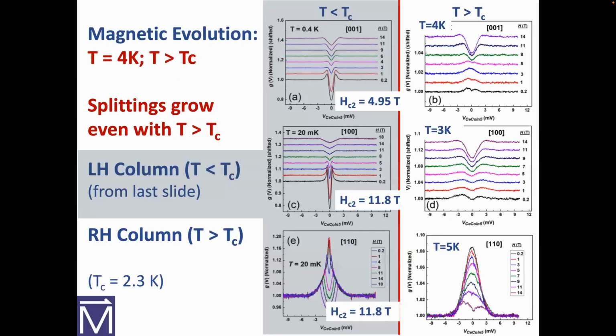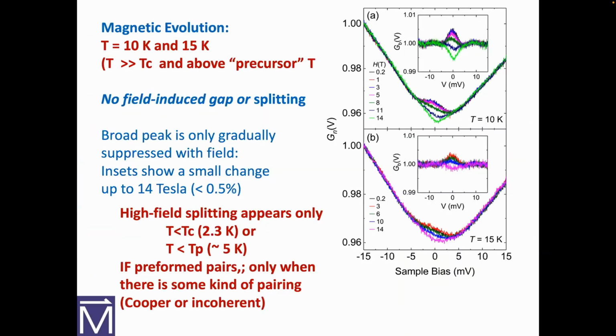Okay, so now the grayed out areas are the data that I just showed you. We have lots of junctions, and yes, this is really nice data, but trust me, it's reproducible. On the right side, the white area, we have T greater than Tc but less than twice Tc. The lead has been driven normal because this is all done in at least 0.2 Tesla. Then we raise the magnetic field, and we see something else changing as a function of field. We're above Tc but below 5 degrees Kelvin. Up to about twice the superconducting temperature, we see the same kind of thing growing with applied magnetic field.